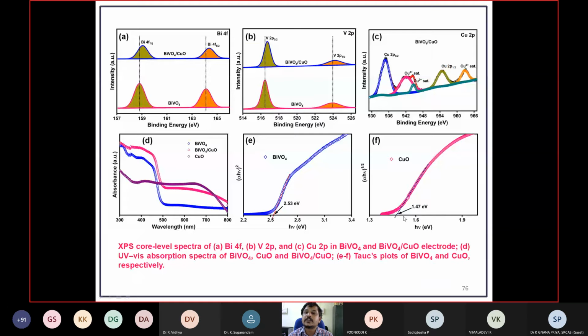Then the XPS analysis also clearly indicates the formation of the heterojunction. If you look at this, there is a slight shift in the binding energy that clearly indicates the formation of the heterojunction for the bismuth 4f and vanadium 2p states. Then the bismuth vanadate shows visible absorption with onset around 500. After making the heterojunction, the visible light absorption is enhanced. We have calculated the band gap by using the Tauc plot method.